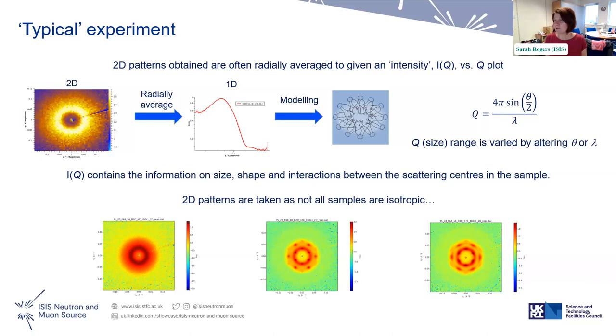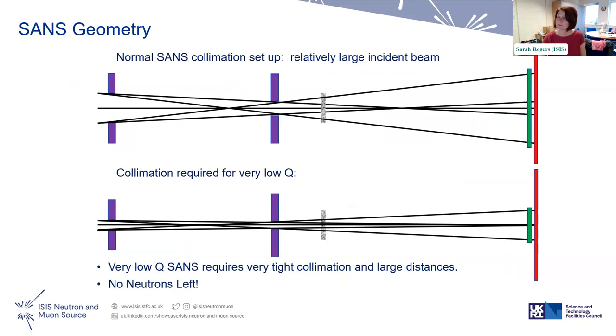The reason that we measure 2D patterns is, normally we collapse down into a 1D plot, but sometimes samples are not isotropic, they can align. So I've shown you here two aligned samples, which are basically a drug that we were interested in measuring under shear, under different temperatures, because often drugs are injected, and they shear in the syringe, and then there can be changes to the structure, which can change the properties of the drug you're injecting into people. We also measured it cold, just out of the fridge, versus room temperature. You can see that in the different systems you do get different scattering patterns depending on the temperature and the shear rate. So that kind of information, we can also get out of small angle scattering. That's why we have the massive detectors.